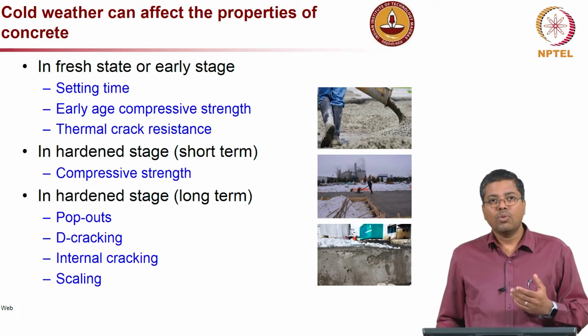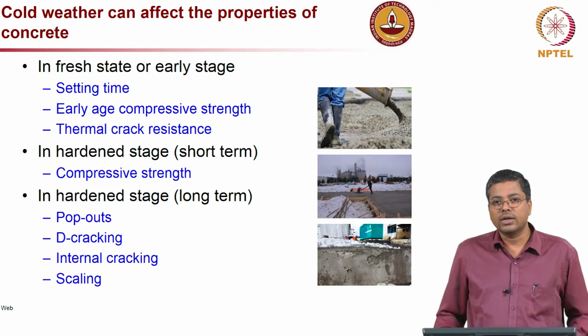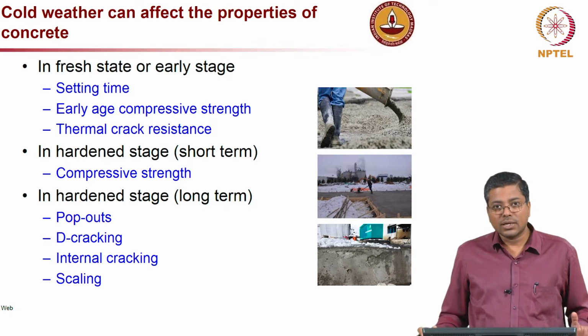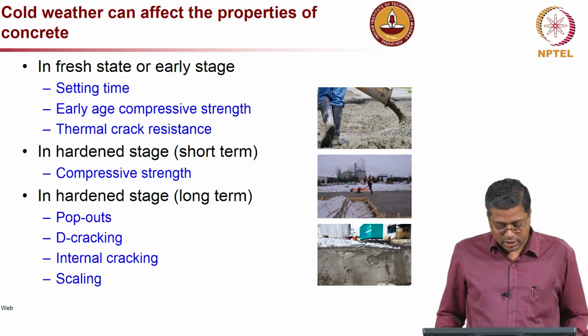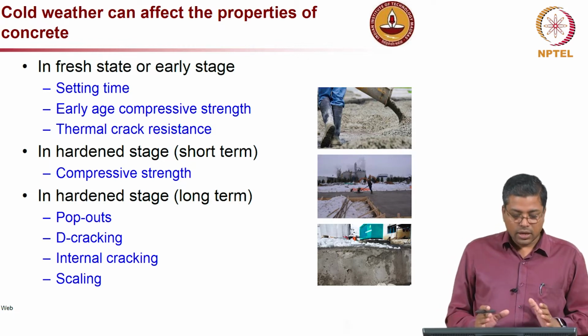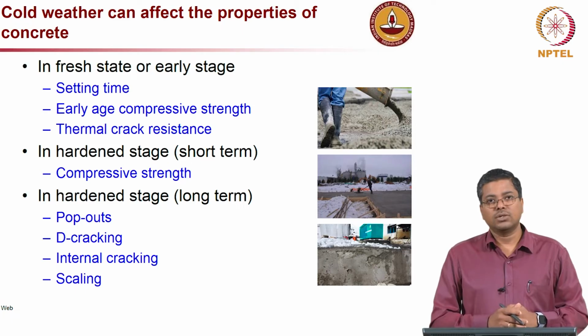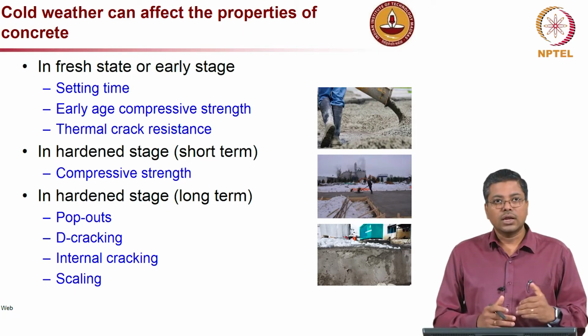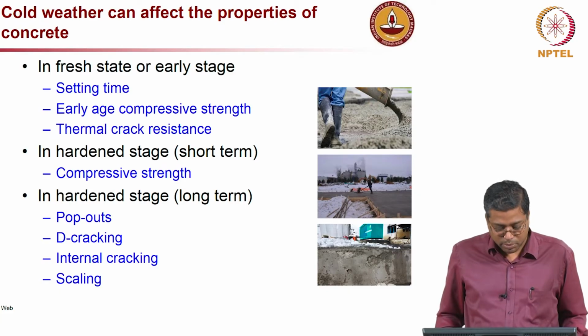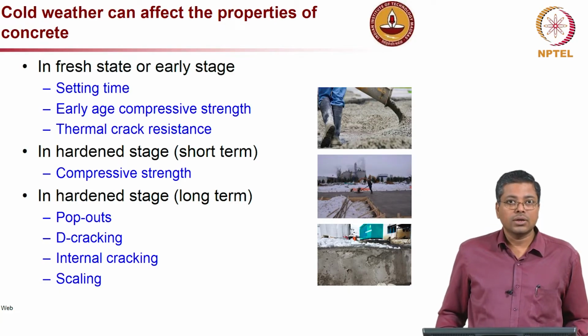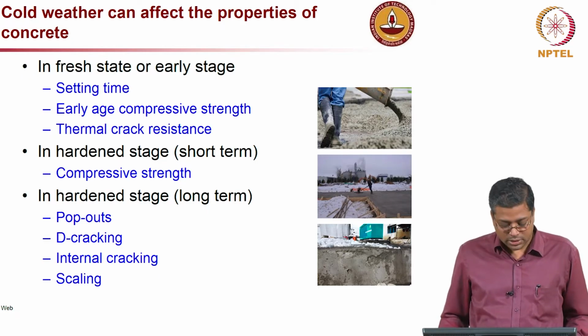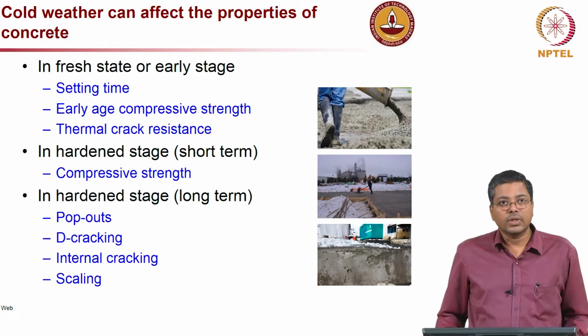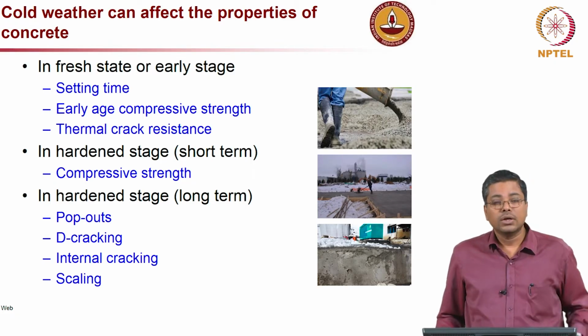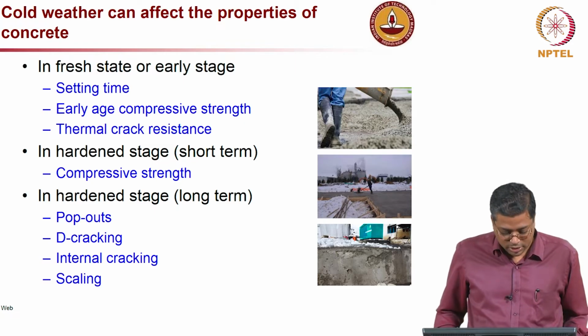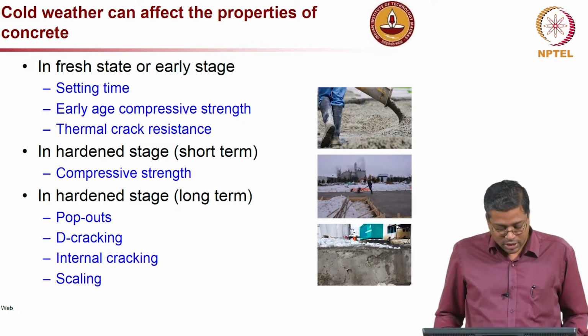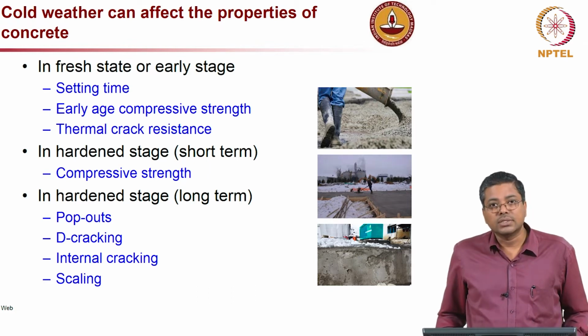I am going to talk about the various mechanisms and the difficulties associated with concreting in cold weather conditions. Now, in the fresh or early state of concrete, there are 3 parameters which are important to consider. The concrete should set as early as possible, and the early age compressive strength also has to reach a reasonable level. Typically we say 3.5 MPa, and then thermal crack resistance is also very important.